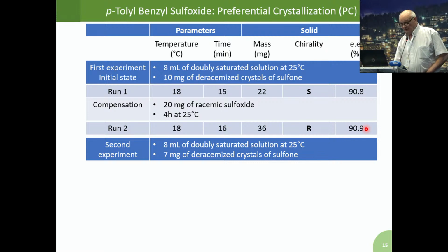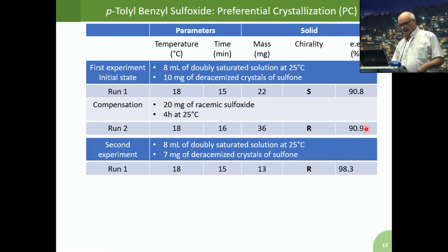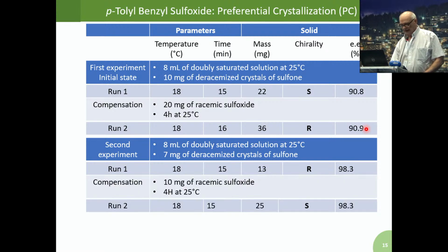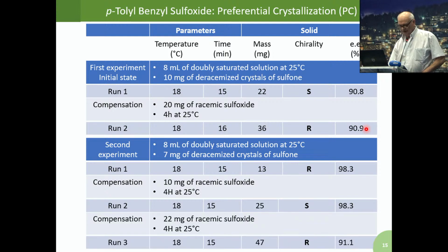And we repeated this experiment with another run of deracemization of sulfone, and fortunately, we got the other enantiomer. I told you it's stochastic evolution. And then by seeding with this other crystal of deracemized sulfone, we obtain much better enantiomeric excess, 98%. And then we recycle this solution, and then 98 again. And then at the third run, we got 91, but with a good yield.